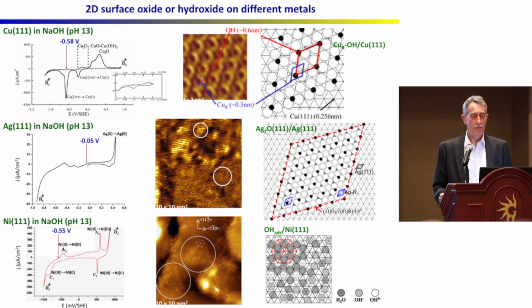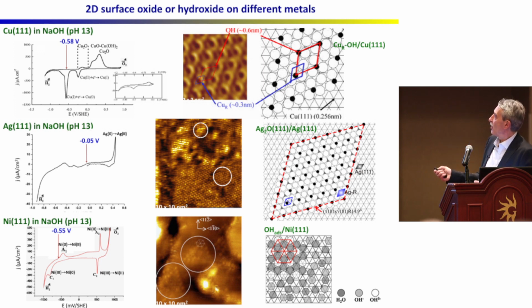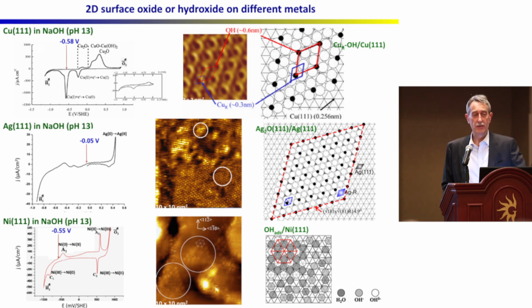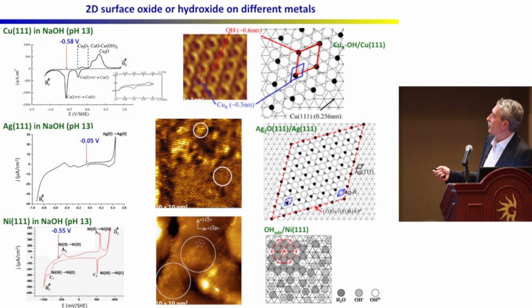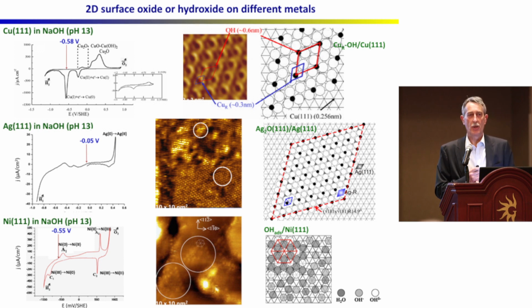We looked at a number of metals, and this is here copper in alkaline solution. And if you scan the potential and look at underpotential with respect to the oxidation, that is in the range where you see nearly no current, except if you enlarge, and then you will see only adsorption. It's a process where you have adsorption of the OH from the water to the metal surface, and this takes place at underpotential with respect to the oxidation of copper. And then if you look at the surface in situ, you find this extremely well organized and ordered surface where you have the copper atoms and the OH from the electrolyte come to this high coordination site, and they form a very well ordered structure.